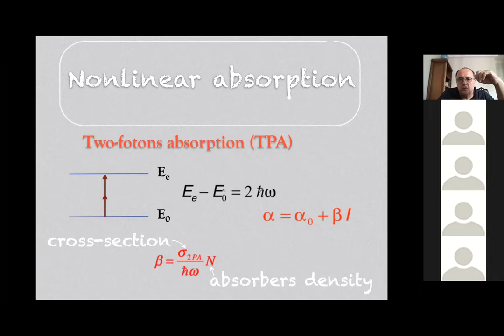So it's a two photon absorption, and you can shine your sample with h bar omega, the energy of one photon. But if it absorbs two photons, you have this nonlinear optical absorption, which has the linear contribution, and beta is the contribution from this phenomenon, the two photon absorption. And this beta is what we can access from our experiments.